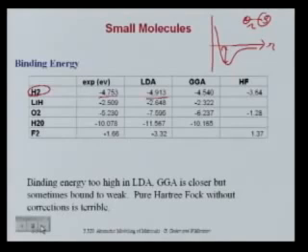You see now that the LDA number, the binding is too strong. So the H2 molecule is bound too strongly. It's not so bad, only about 5% in hydrogen. And in the GGA, the binding is too weak. For reference, I've also put uncorrected Hartree-Fock in here. Professor Marzari showed you essentially what Hartree-Fock is, which is having the Hartree term, the self-consistent Coulomb interaction from the other electrons, and the exact exchange, but no correlation effects.